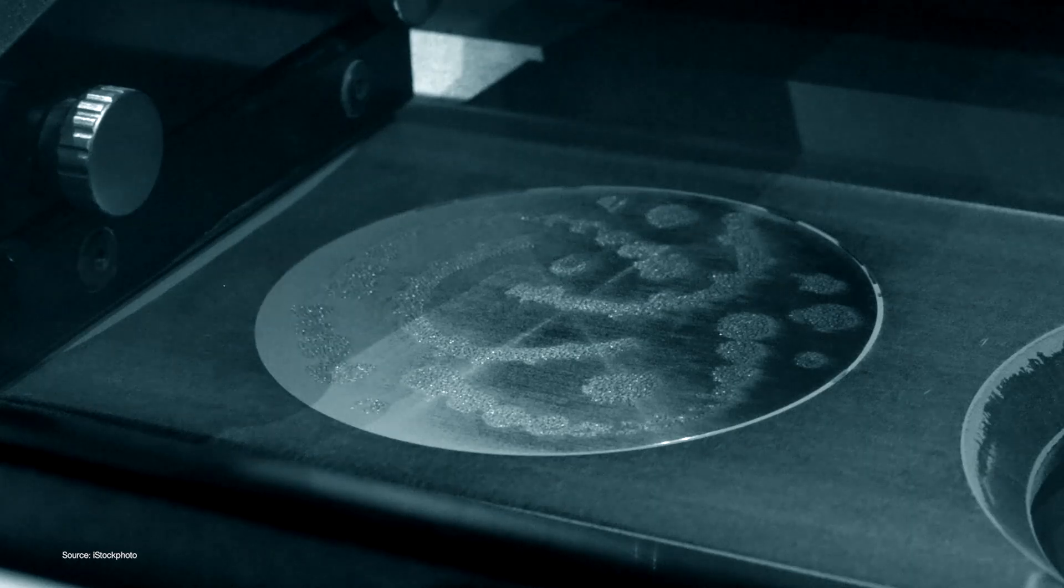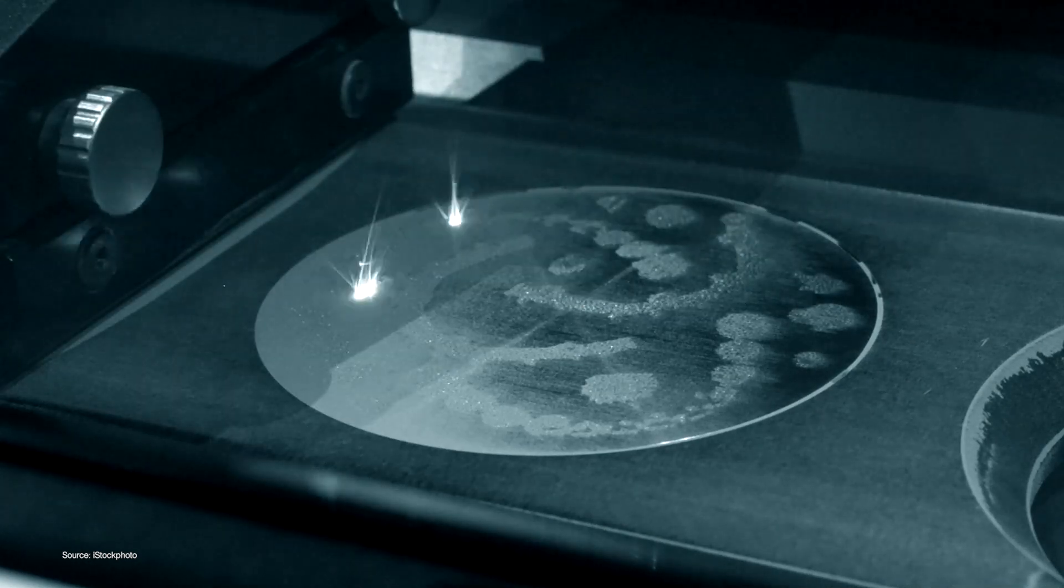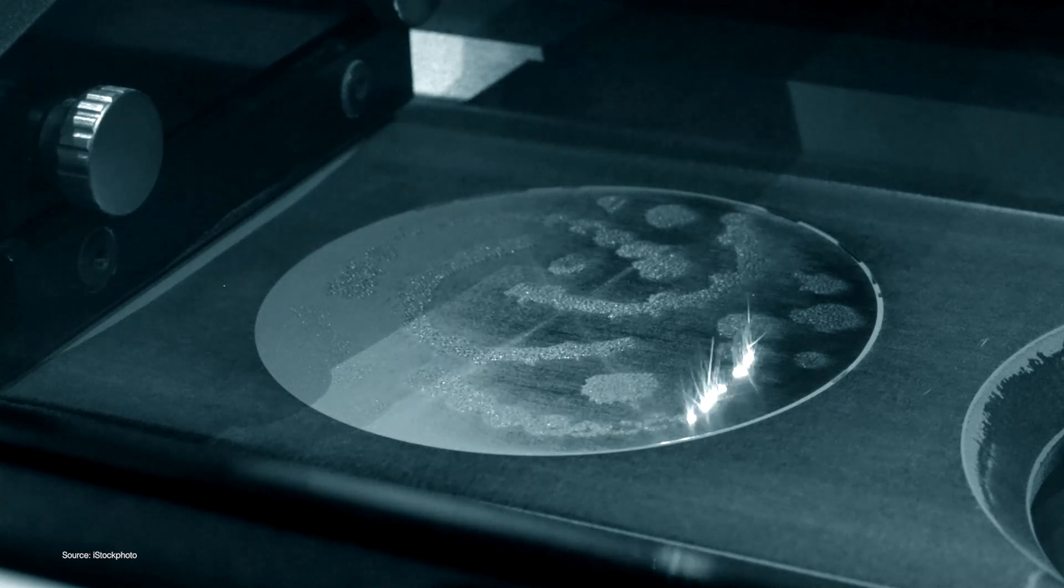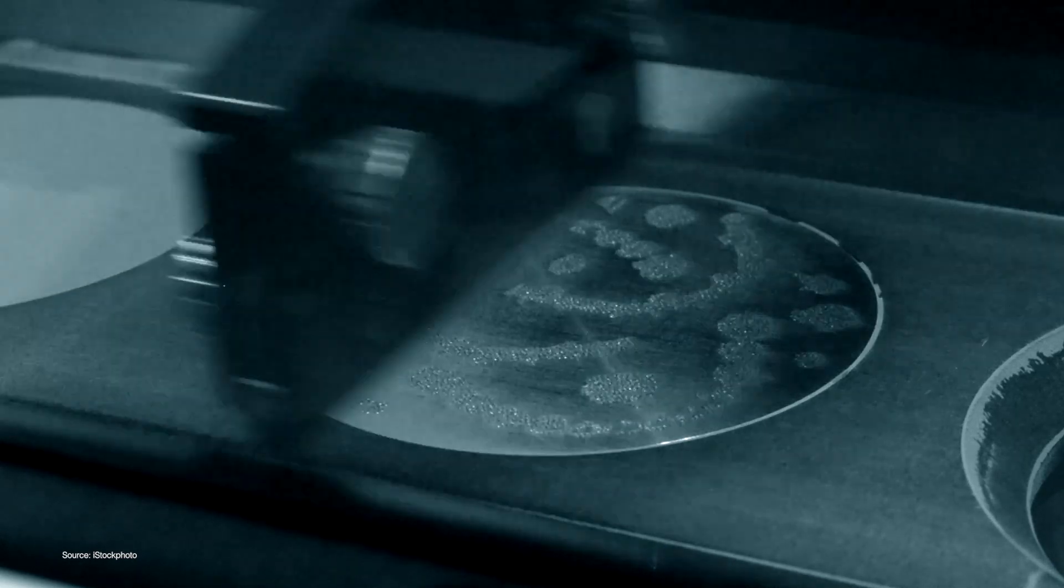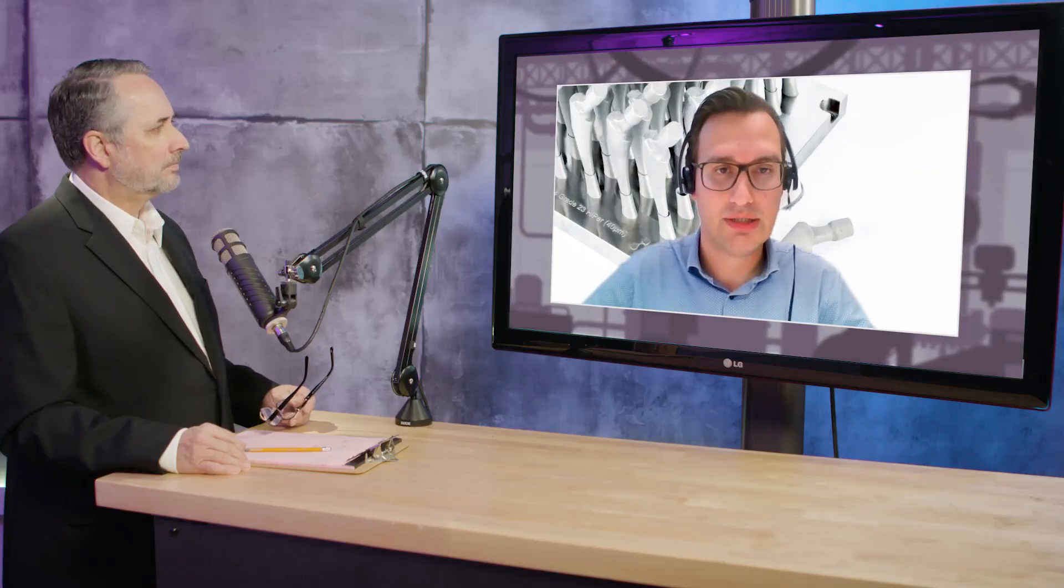Lastly, because of what I mentioned before, this local energy input creates quite big thermal gradients in your part, which then results in thermal deformations. Supports can help you either deal with those gradients and lower those gradients, or prevent the deformation that can happen.